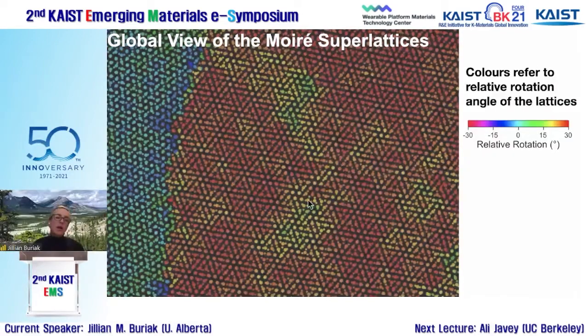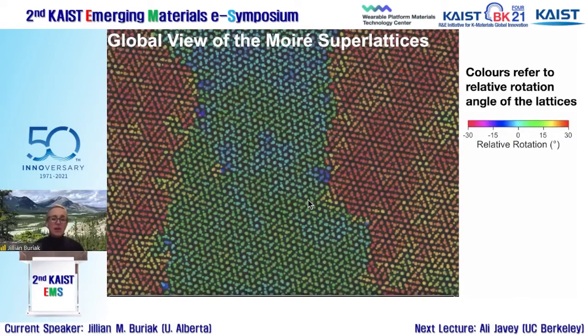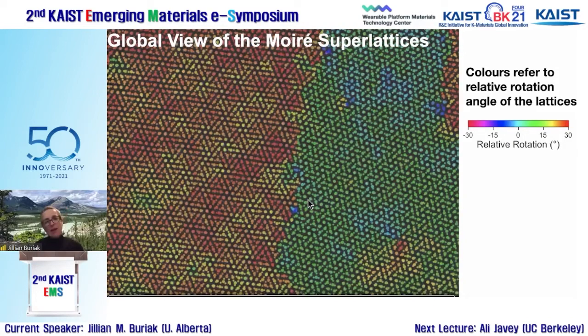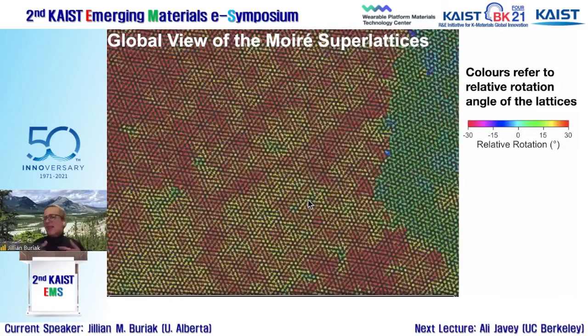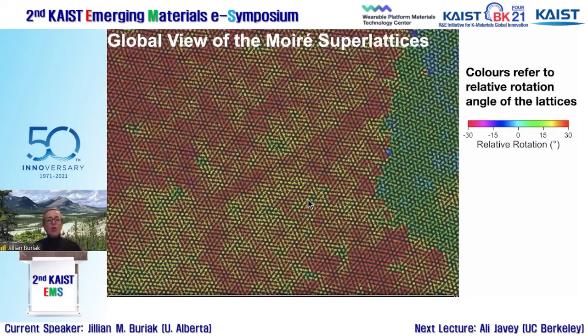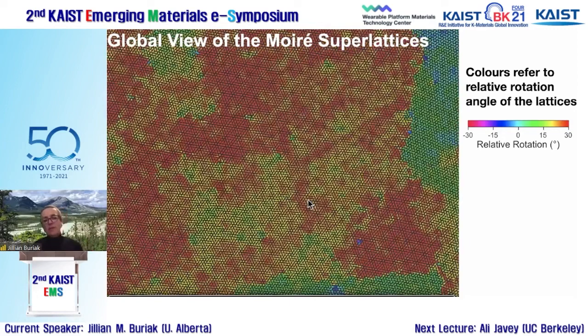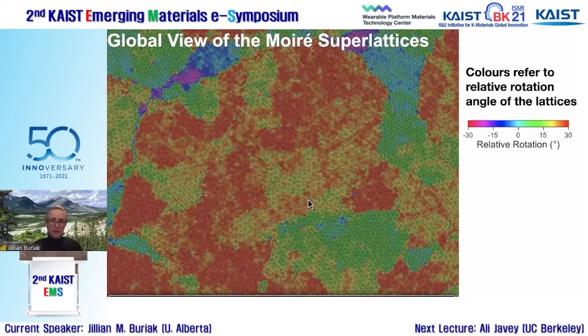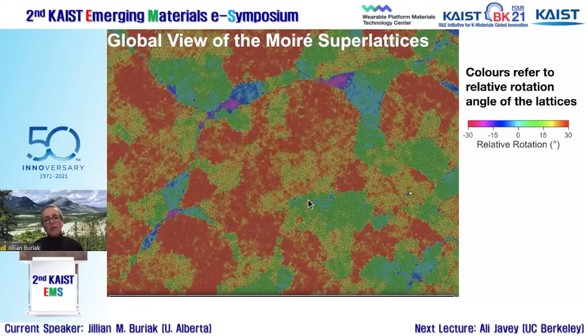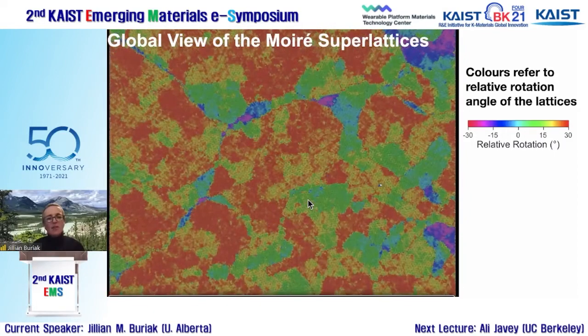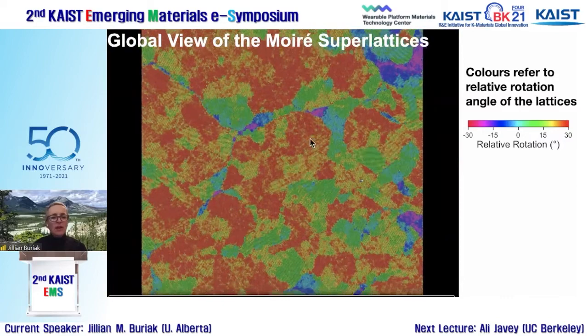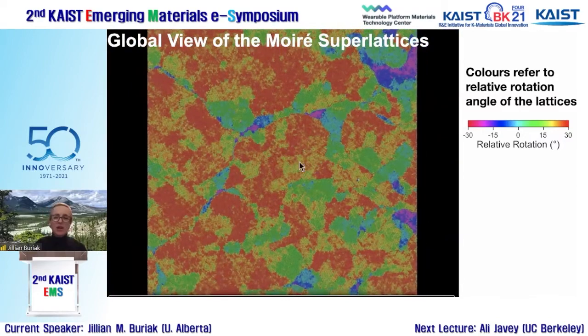And so what this allows you to do is to take a very large image and then again be able to statistically analyze and look to see whether you are simply getting a mess of things or are you getting a majority phase? Does the system find the lowest energy configuration? As you zoom out of this kind of Google Earth type viewing of this 30 micron by 30 micron image, you can actually see that the majority of the phase is, you see a lot of this red. And so that's telling us this is a majority phase.